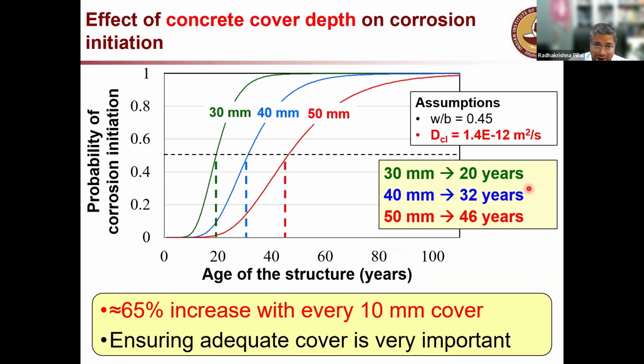Now, another thing which we often neglect is the cover depth, which I believe is probably the most important thing one should worry about. See, the advantage of having a good cover in a concrete structure. So look at this box here on the right side in this study. 30 mm cover, let's say you get 20 years life. 40 mm cover, you get 32 years life. 50 mm cover, you get 46 years. So the thumb rule is for every 10 mm, you can get about 65% increase in the service life. But it doesn't mean that we can keep on increasing the cover, because the concrete will crack. So you have to design that optimally.